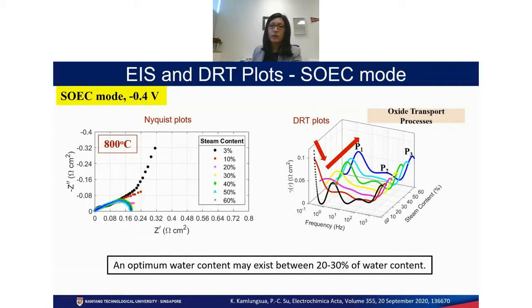Okay, so we feel that there will be a more optimized or more suitable amount of water content around 20 to 30% that will exist. Okay, so meaning that if you have too much water content, it doesn't really get taken up by the electrode. Too little, they also cause the impedance to be high.